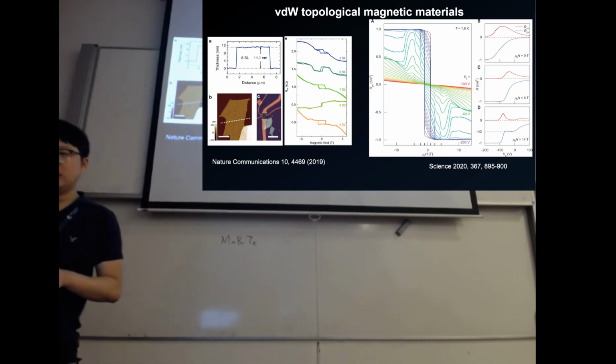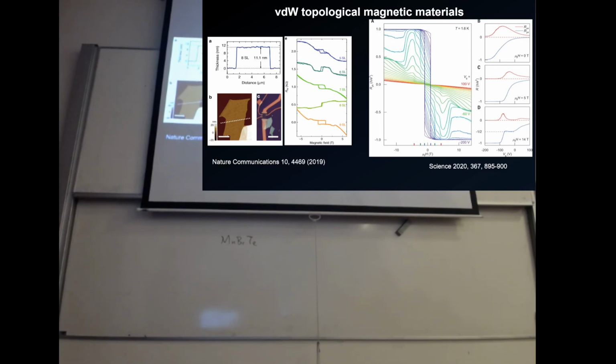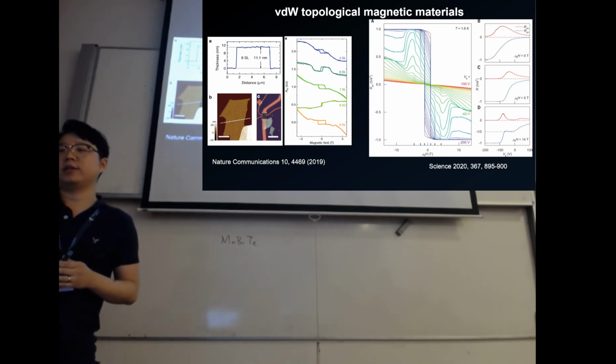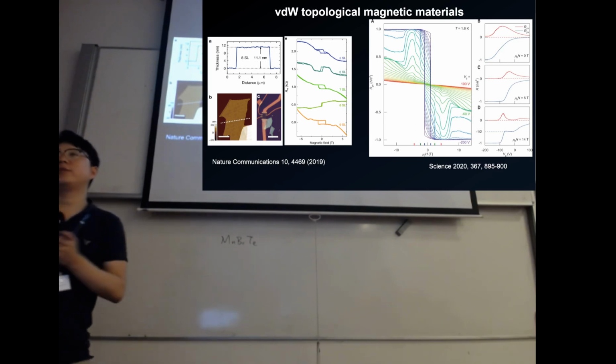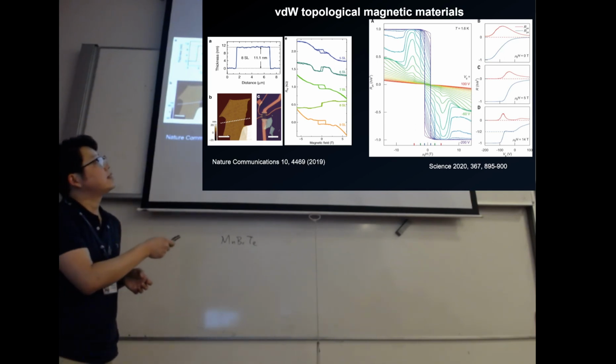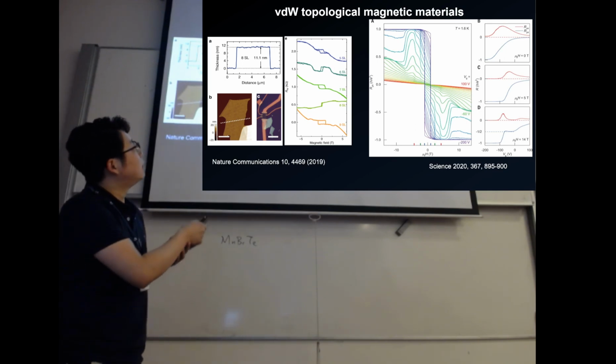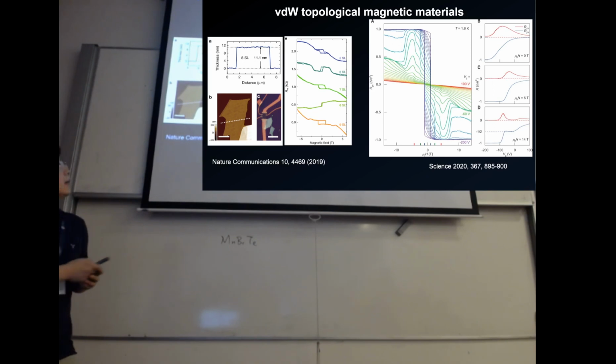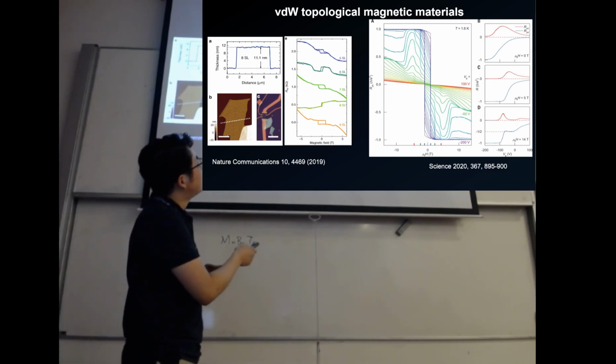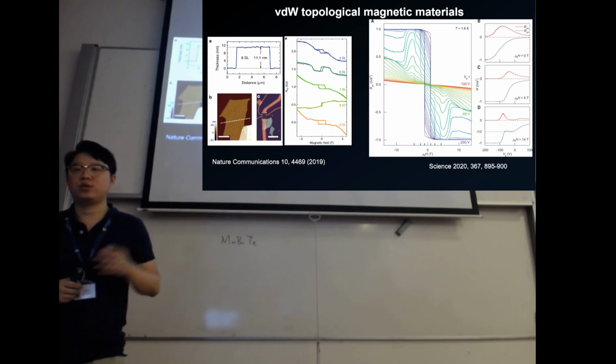And this compound, according to some experimental investigations, has very complicated magnetic phases. Especially when you put this material in the ground state and apply some kind of vertical electrical field, the system can be tuned as a field effect transistor. At the meantime, the magnetic phase can also be tuned. For example, this one is Rxy, which is the Hall resistance, and the colors are representing different gate voltages. So basically, it's a field effect transistor. The x-axis is the external perpendicularly applied magnetic field. And we can see that at some gate voltages, which are very negative, like minus 200,